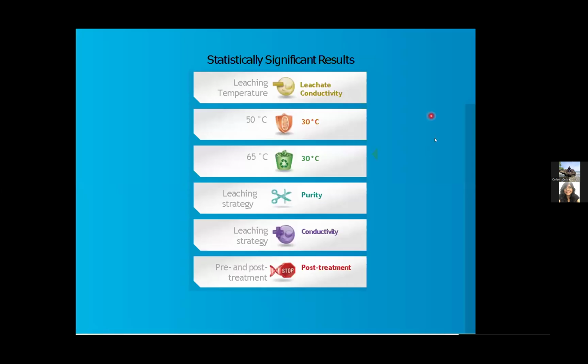So just to recap, which nasabi ko na rin po kanina, is yung statistically significant result is that the leaching temperature changes leachate conductivity significantly, and there's a significant difference between 50 degrees leaching temperature and 30 degrees, and also a significant difference between 65 degrees and 30 degrees. So the leaching strategy, yung type ng water leaching treatment, significantly changes the purity, and also significantly changes conductivity. And then there is also a significant difference between pre and post treatment versus post treatment alone. So because of the crystallization of silica na nangyayari po sa pre-treatment.